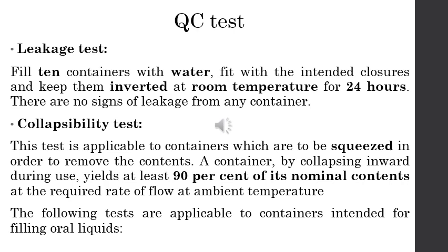The next test is the collapsibility test. This test is applicable for containers which are meant to be squeezed to remove the contents. A container, by collapsing inwards, should yield at least 90% of the content at the required flow at ambient temperature. The next slide shows the QC tests for plastics which are used to fill liquid orals.